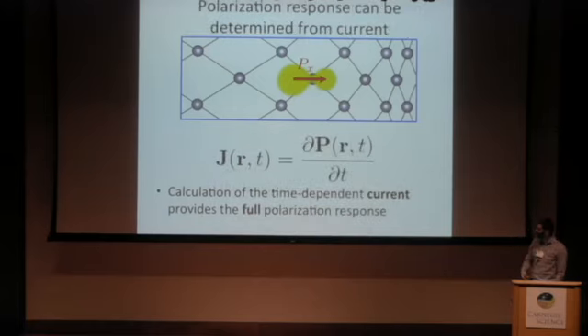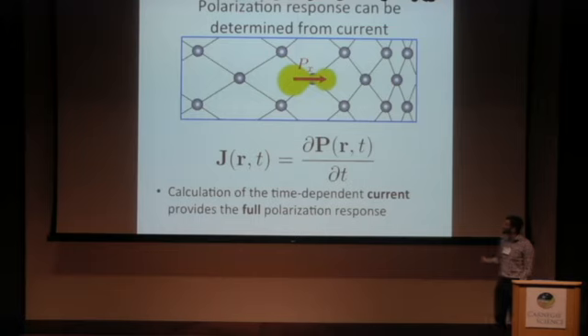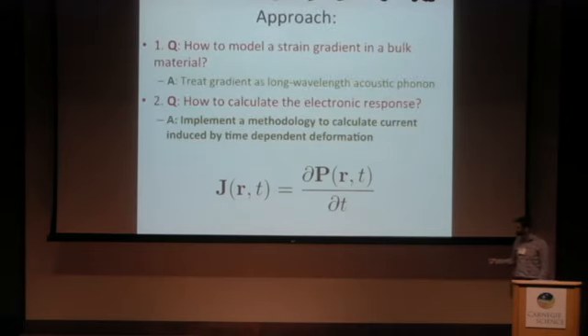If we want to calculate the full flexoelectric tensor from a bulk calculation, then we need to instead consider the current density that's induced by a time-dependent motion of atoms, which we know from electrodynamics is related to the polarization in the following way. So this current density is not something that is normally implemented in density functional theory, and so we have to develop our own methodology for these calculations. So in the next few slides, I'll just briefly touch on a few aspects of this methodology.